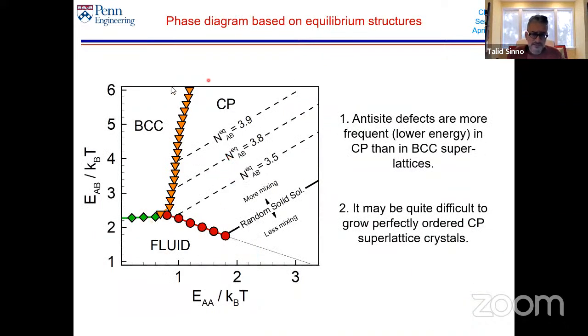So this is a phase diagram for what you would expect to see. This is the interaction between A and B. Think of this as the dominant interaction. And then this is the interaction between like particles, so either AA or BB, doesn't matter. So when the interaction is low, you don't get any assembly. As you crank up the interaction, you form this BCC, or cesium chloride, phase. And then at a given interaction between A and B, as I move this way, I'm increasing the attraction between like particles. I cross this line and I enter now the close-packed equilibrium phase.